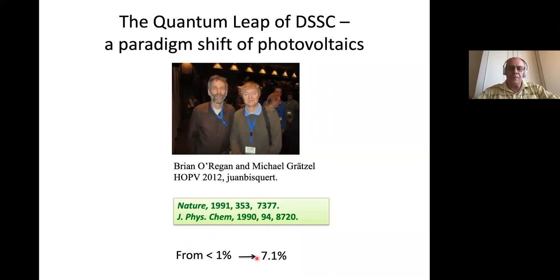And the big secret was that one could use these nanoparticles to form a high surface area, even porous system, which means that you can absorb a lot of dye molecules, and in that way you can harvest sunlight in a very efficient way. The paradigm shift which happens here was that if you read a textbook on how to make efficient solar cells like silicon, what you should absolutely not do was to use a high surface area electrode. So this changed completely the game of how to make efficient solar cells, entering also chemistry and simple laboratory techniques for how to make solar cells. So it was truly a paradigm shift, creating a lot of excitement.